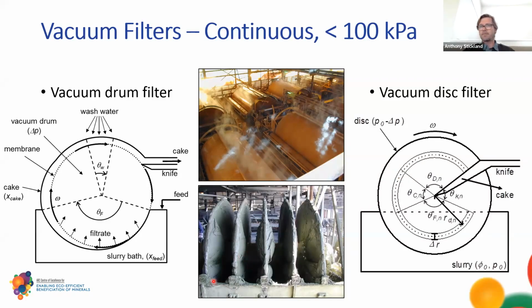Vacuums are of course limited to atmospheric pressure. And so if I've got a very, very fine particulate material, then the vacuum is not going to be sufficient to, for example, desaturate the material. If I get down to about 10 microns, depending on the surface tension and various other things, I'm going to have a capillary pressure in the pores that is of order 100 kilopascals. So I'm never going to be able to desaturate the material. I would need a hyperbaric version of these, which do exist. So they put the entire drum or the disc stack into a hyperbaric chamber so they can get larger pressures.